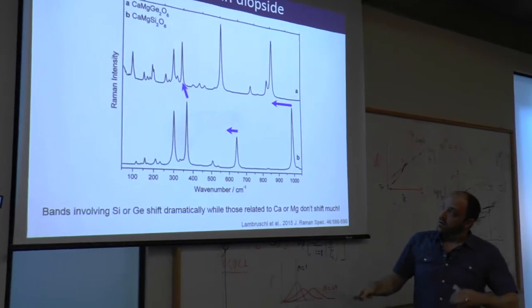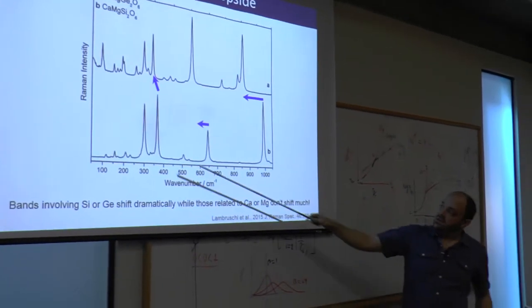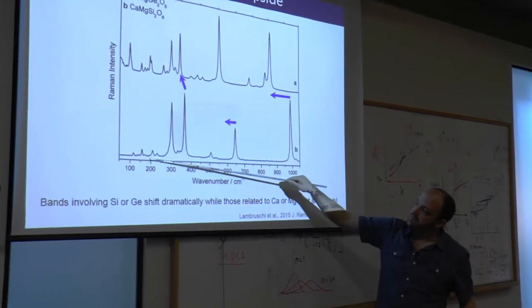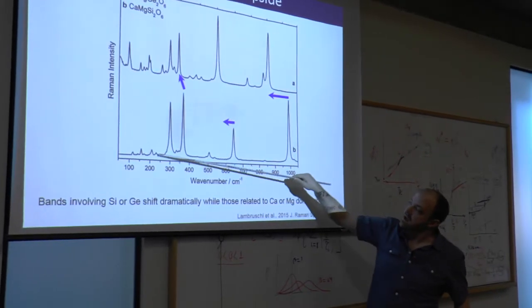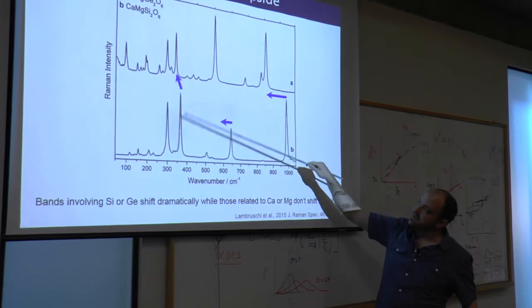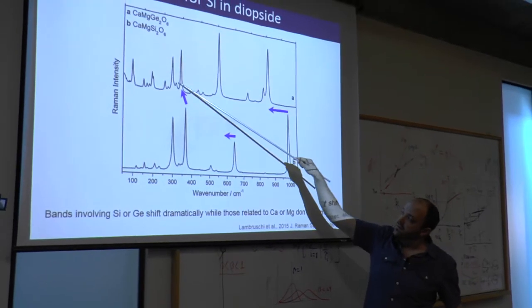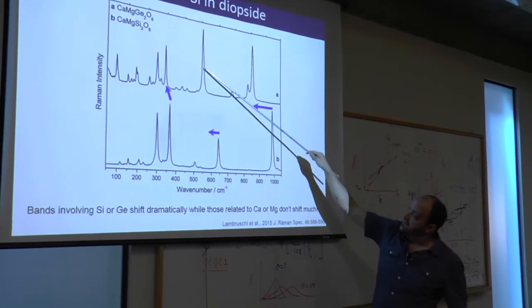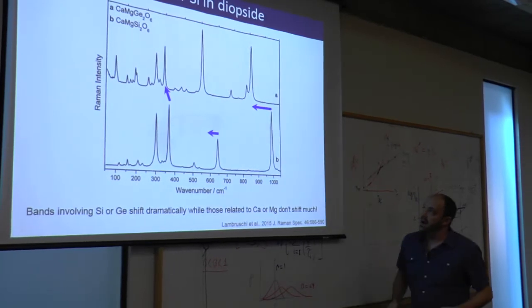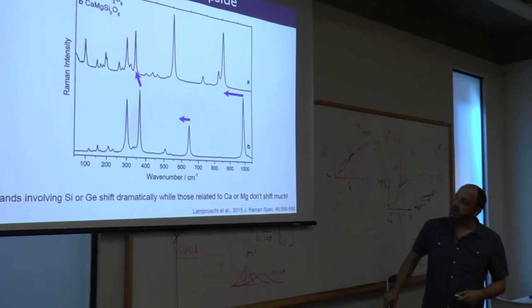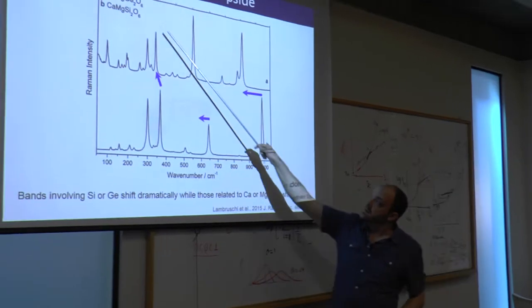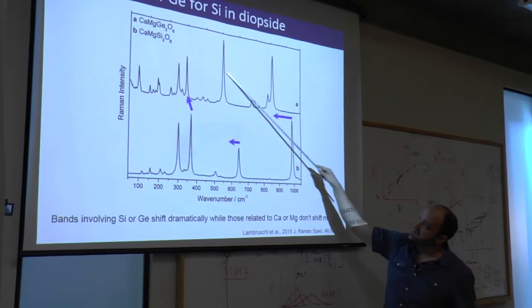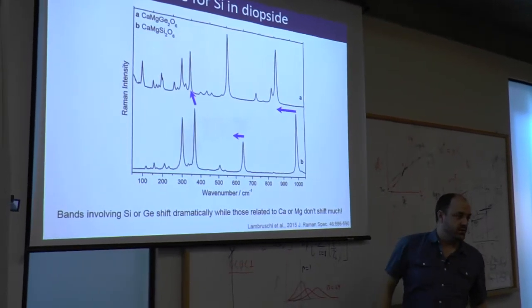If you just look at the spectra, there's the same overall pattern. We have some peaks, with some subtle differences, but we have two major peaks with a couple of small ones in between. In the low frequency part of the spectrum, we have two major features at much higher wave numbers, and we can see that in the sample with germanium, the frequencies are all shifted, all compressed towards lower frequency.